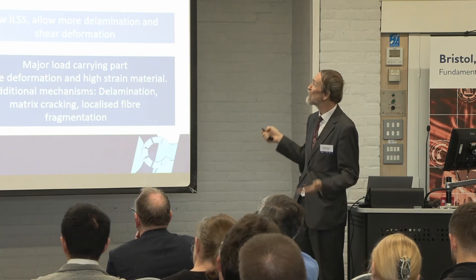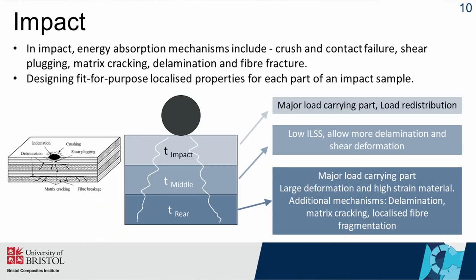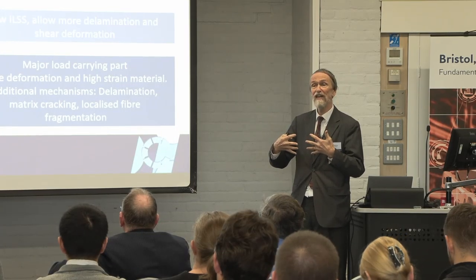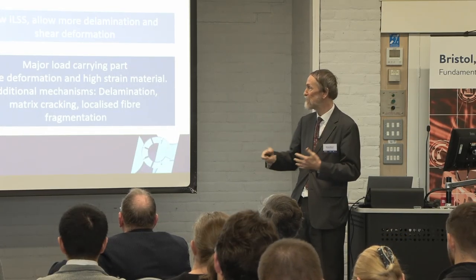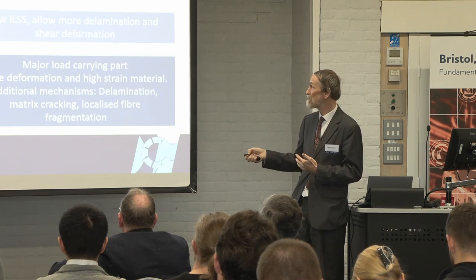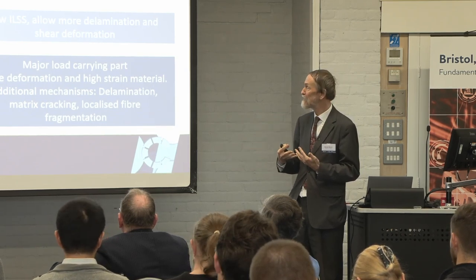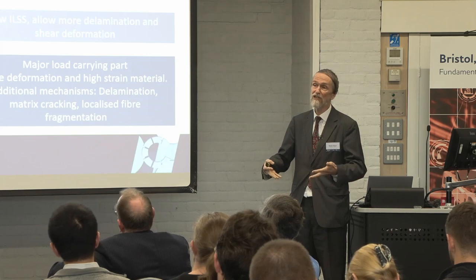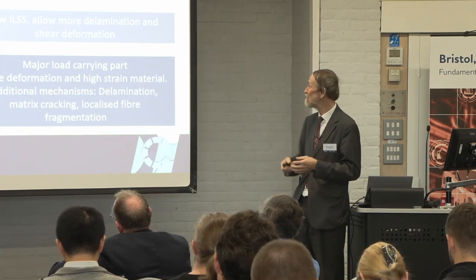For example, you may want to have on the compression surface the ability to take the load and redistribute it. In the middle, it may not be so important to have the high strength because if you have failure and delamination, it reduces the stiffness, which enables taking larger energy because you get more deformation. And on the back, you want good tensile response and you want the ability to take large deformations and carry load in tension rather than in bending.